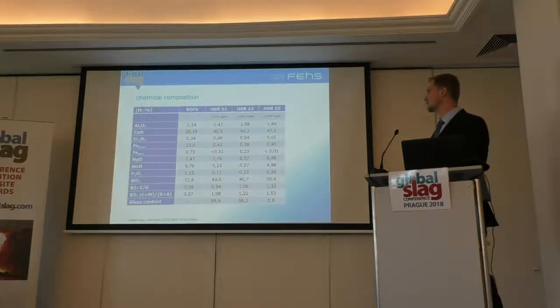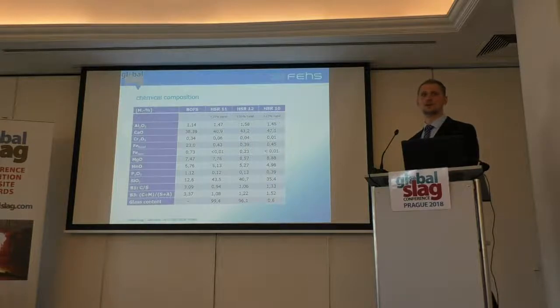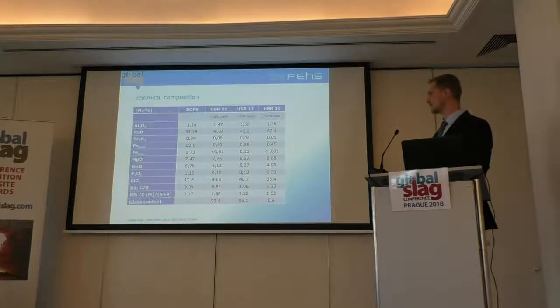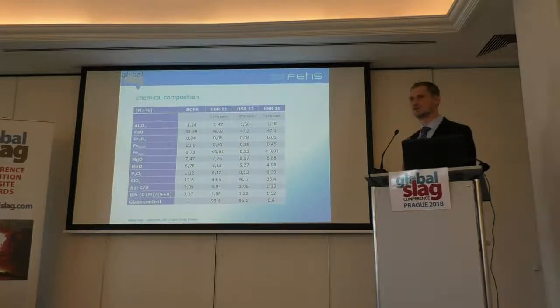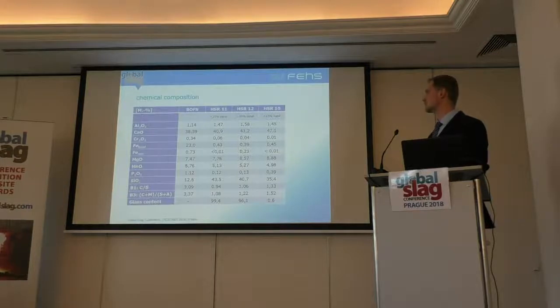So when we're looking to the chemical composition, we started in the first trial with 25% sand to be sure, okay, we are very, very low in basicity, and to guarantee that we have a glass. So we looked to the glass content. It was more than 99%. Everything is good, but with the CaO/SiO2 basicity we were below 1. So very, very low, and this means there are bad properties in the cement.